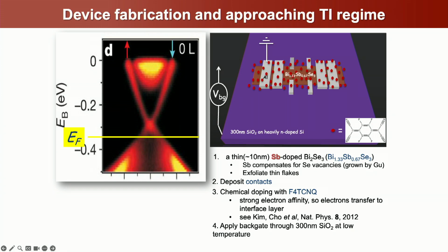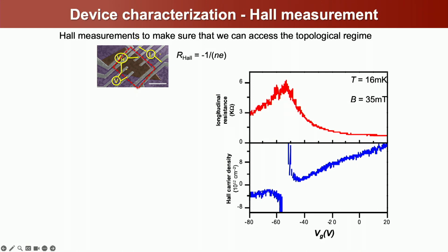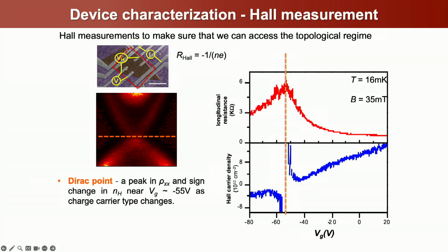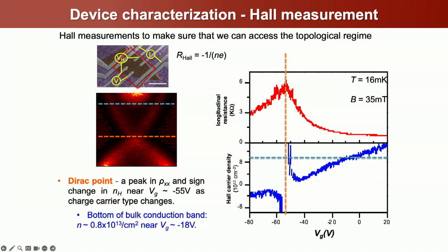So this is the sort of transport data we see. This is resistance as a function of the back gate for a flake of bismuth selenide, you can see here, which has chemical doping on it and a back gate. And as a function of the gate, we can now access the Dirac point. And if you measure Hall measurements, you can see where it changes sign. So we can clearly gate all the way through the Dirac point in these systems. And then we can now differentiate between where the bottom of the bulk conduction band is and where the topological region is to really differentiate behavior.